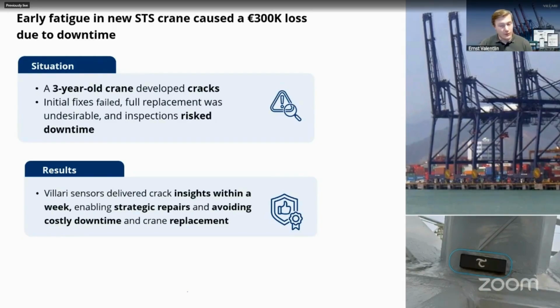In this case, after doing that reporting for a while, they did an additional inspection. They found very minor cracks right next to the sensor strips where we were seeing this activity. But more importantly, they were able to relate the times when we were seeing these very high bursts of crack growth back to some very specific occurrences in the way they were operating this crane. So to actual events happening to the crane